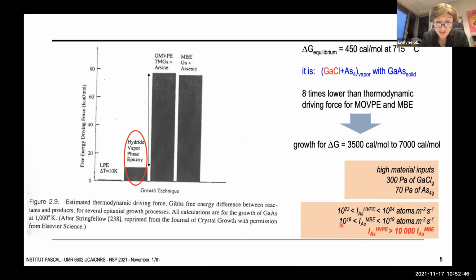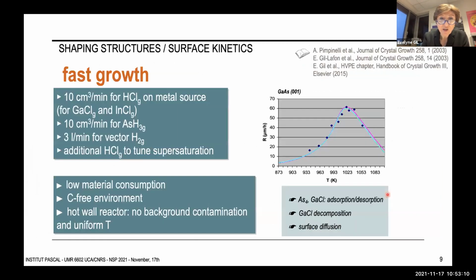And another feature is to be emphasized, as HVPE is usually carried out with V/III ratios higher than 1, and this is of course related to the significant desorption of the volatile gallium chloride species, and that's why HVPE is usually carried out with an excess of element 5 in the input vapor phase. So this highly reactive system needs very few material. It is supposed to be carbon free, and the hot wall reactor prevents absorption of contaminants.